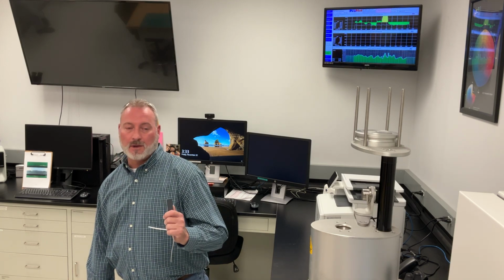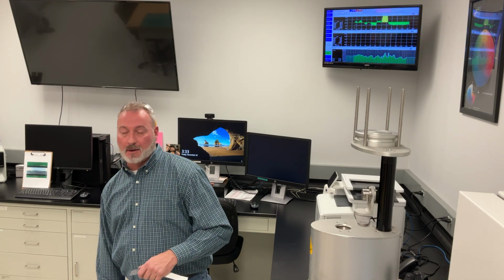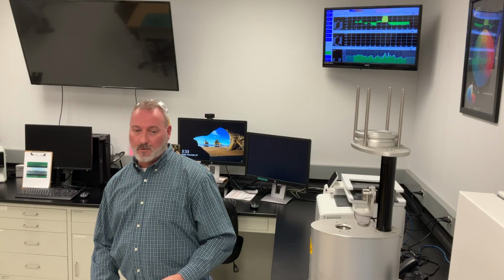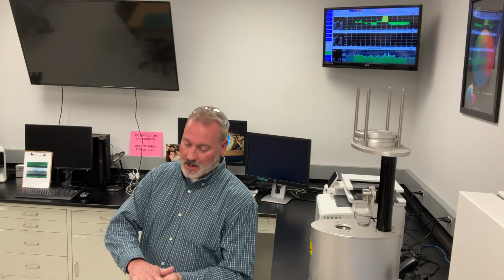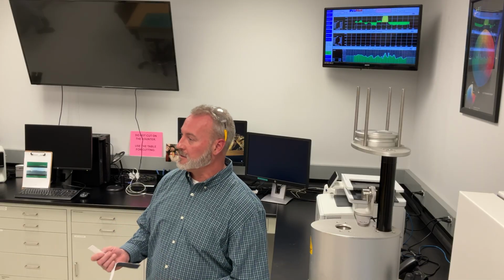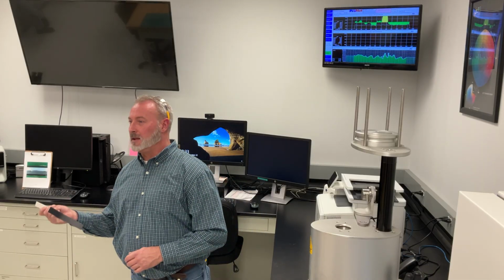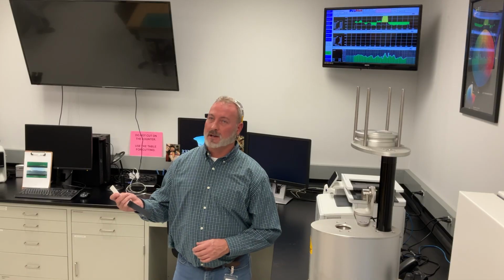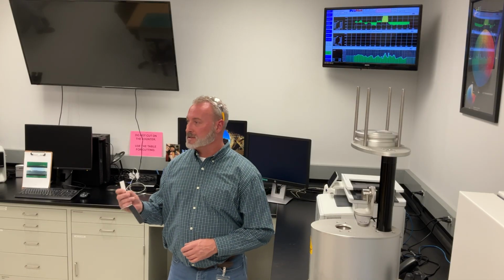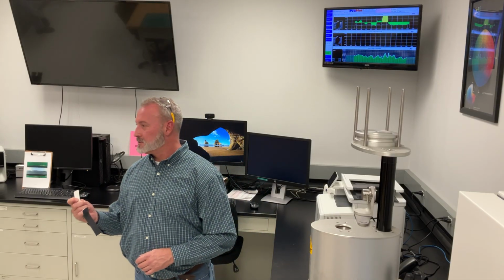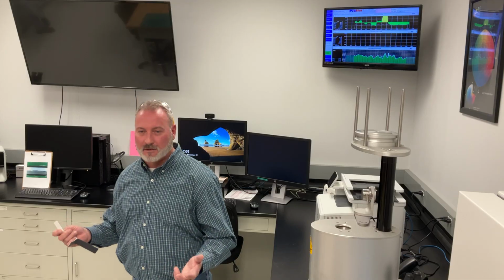On top of that, we do what's called a hydrostatic burst test, where we put a sample in between a hydraulic press, and then we shoot water through it to see how much PSI it takes to break the membrane. The last sample I looked at, or test, was 525 PSI to break that membrane. The spec is around, what, 400?